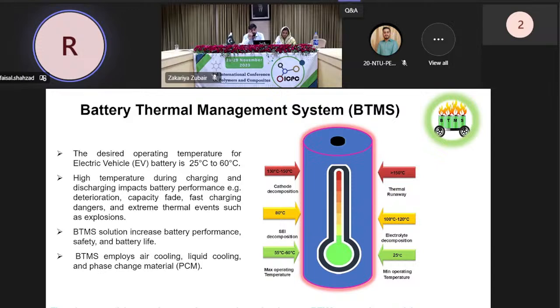So we have to keep the battery in the desired operating temperature range. Otherwise, between 130 to 150 degrees, cathode decomposition occurs. If it's more than 60 Celsius, then SEI - solid electrolyte interphase - decomposition occurs. That's why we have to operate the battery in the nominal temperature range between 25 to 60 degrees.